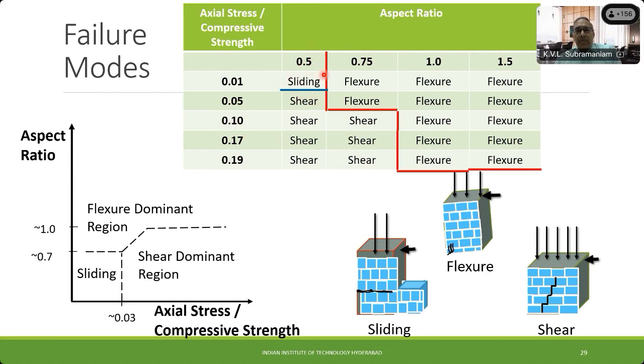Now, for a very squat wall, where the aspect ratio is 0.5, at a low compressive stress, low vertical stress, we see a sliding type of failure where the wall basically simply slides off from the bed joint. When I increase the aspect ratio, I get into a flexural mode of failure. But when the wall is squat and the compression is high, as the compression increases, we also get a shear mode of failure. Shear mode of failure where you have a diagonal crack that runs through the masonry.